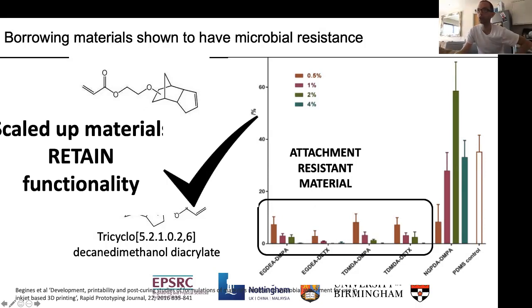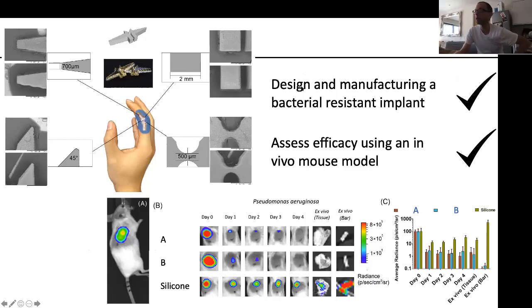So we were able to take from a screen, identify materials, and then we were able to show that you could print them and that they retained functionality, at least in vitro. And then we went to the next stage, which was to do in vivo studies. So we constructed an exemplar, we made samples ready for in vivo studies, and then we tested those within a mouse model. And we saw that our formulations, despite having a really hefty dose of bacterial infection inoculation, cleared out the infection in vivo really well compared, 3 orders of magnitude compared to medical grade silicones. So we're really happy with that.